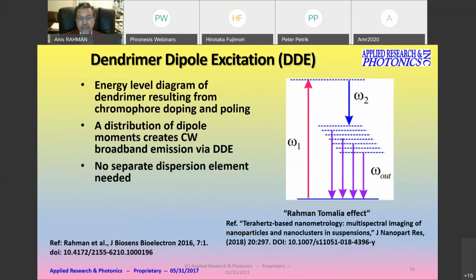And this emission is broadband emission because the quasi-stable states formed in the Fermi gap are not a single one. Because of the dipole moment distribution, in the Fermi level, you have more than one quasi-stable state. Therefore, the output terahertz radiation has a distribution. We have been able to generate up to 30 and more terahertz out of this system.